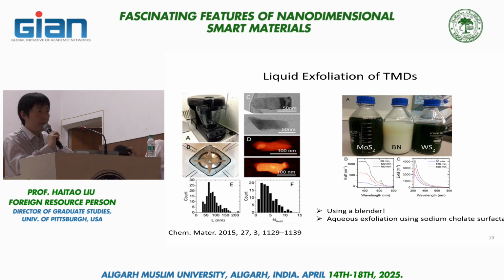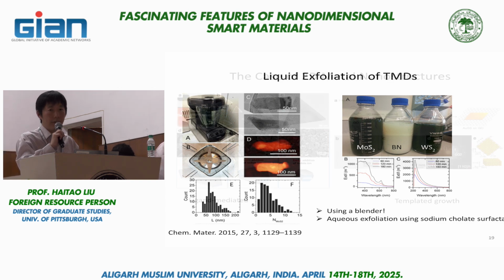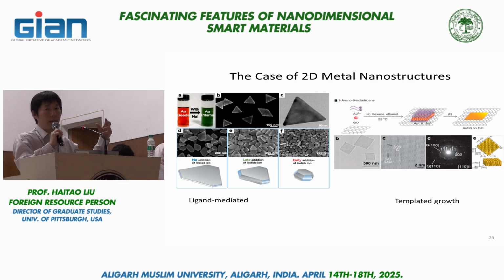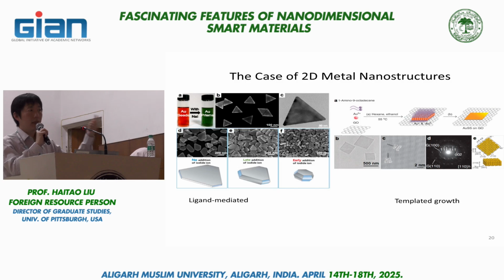One is the so-called bottom-up approach. You can do a lot of colloidal synthesis, and on the left is one such example. You start with spherical gold nanoparticles, and you add some iodide, and magically the nanoparticles will transform into plates. The reason is that some small molecules, iodide and bromide in particular, adsorb to certain crystalline facets of gold, so that growth along those directions is limited. Instead, they can only grow in certain other directions. That can produce this plate structure, and there's a variety of metallic structures you can get in this approach. Silver, gold, platinum are examples I can think of right now.